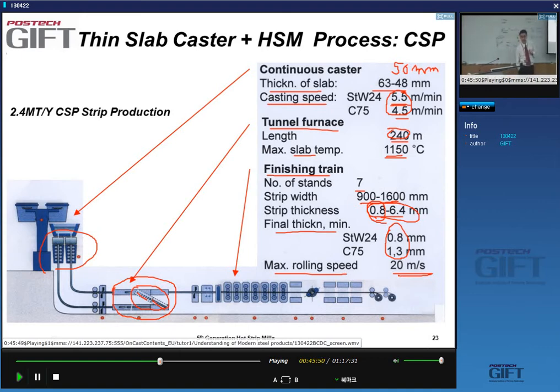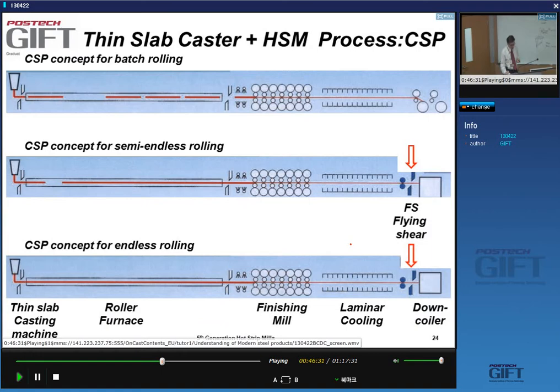Remember, one of the reasons you do want to roll fast is there are metallurgical grades, such as the high-strength, low-alloy grades, where it's essential that you achieve very small interpass deformation times, yes? And so that's one of the reasons why you need to achieve these 20 meters per second. But in a conventional hot strip mill, the exit velocities can be much higher.